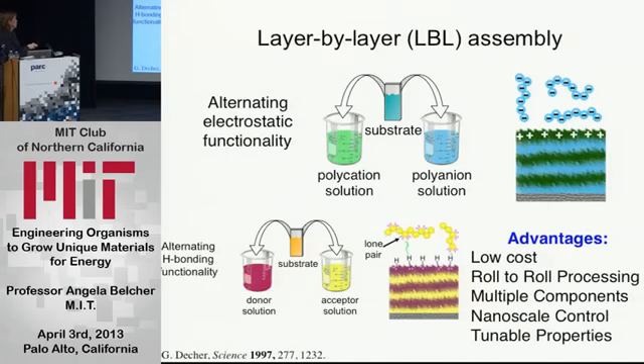You take a substrate, or you spray it, or in this case, you dip it in the cation, anion, cation, anion, and you can build up these layers, these nano-structured layered polymers. And then we engineered our virus to like these polymers, and wanted to use this as a surface to be able to grow materials.